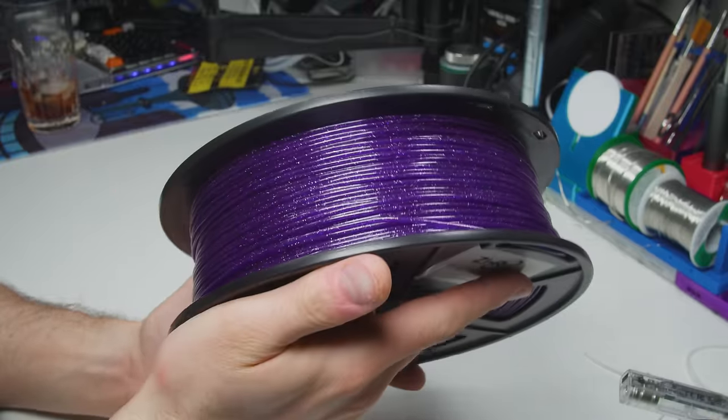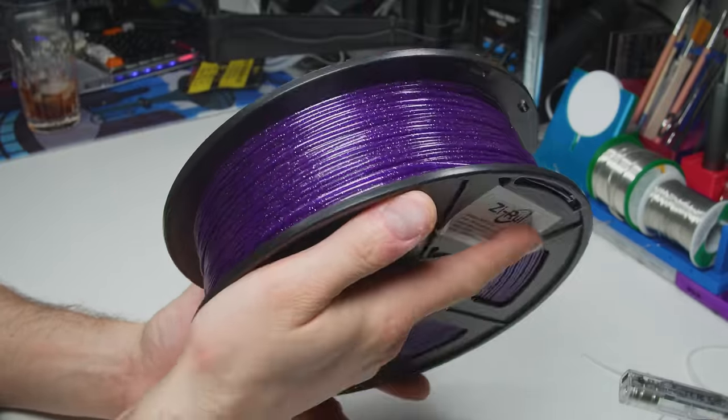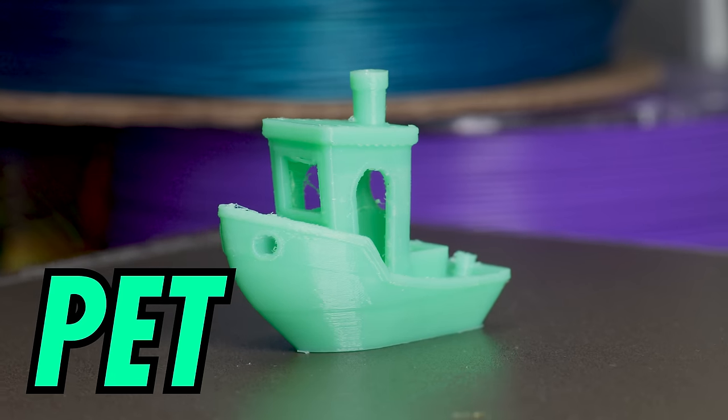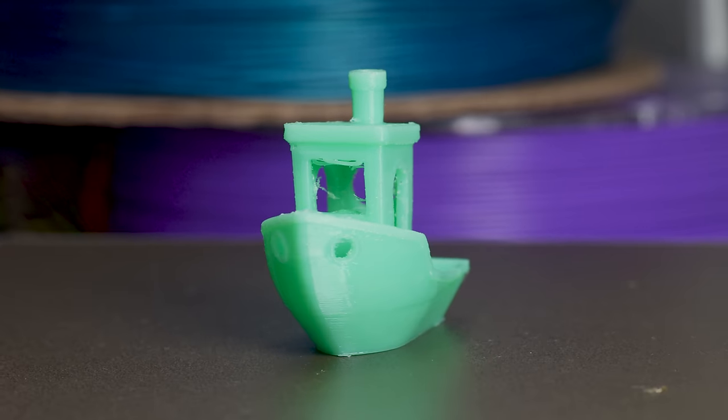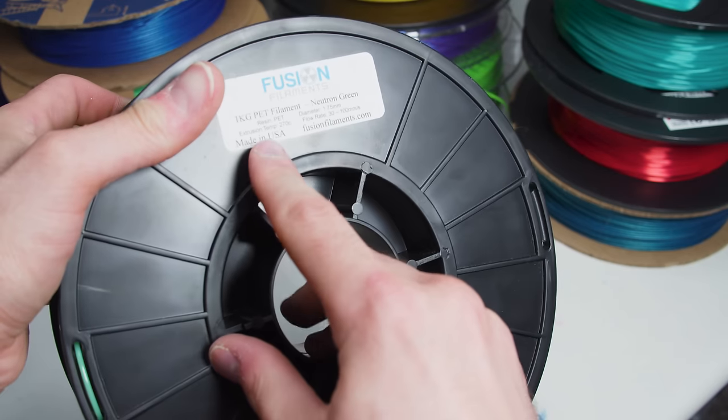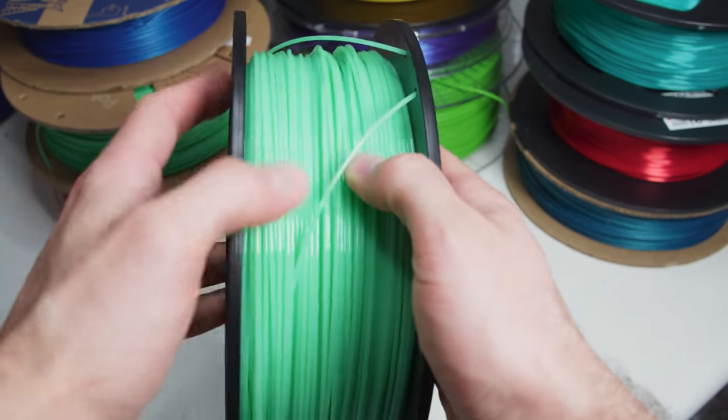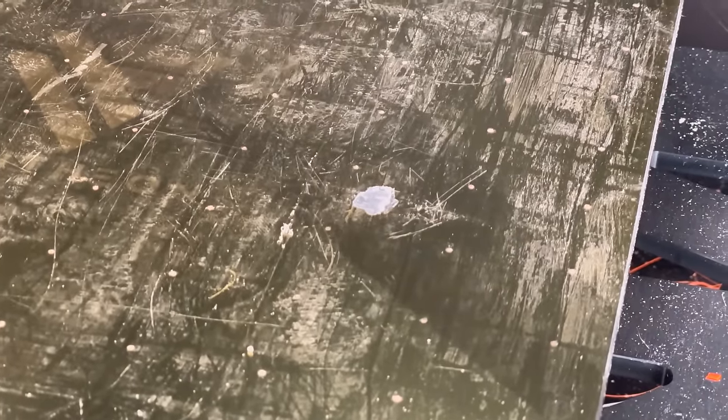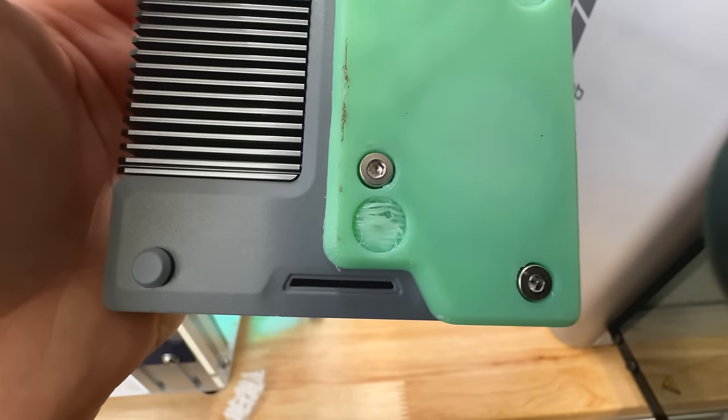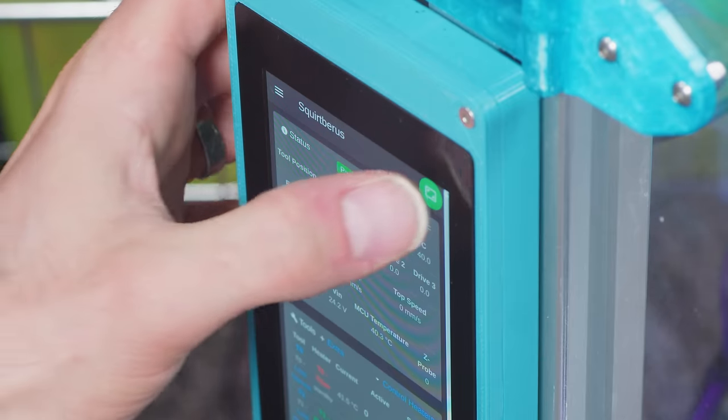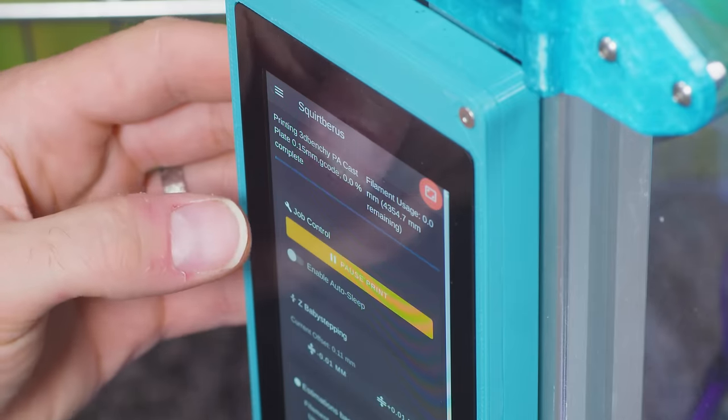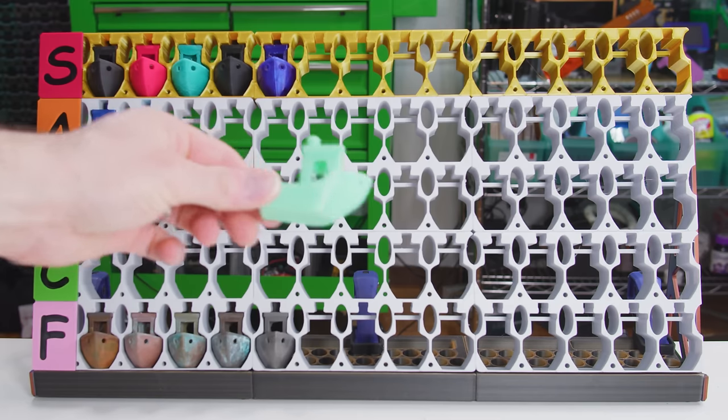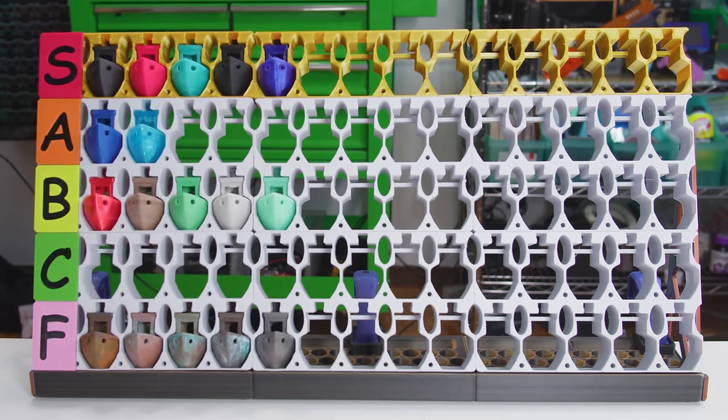That last letter, the glycol, makes the polymer more flexible and easy to print. But if you want to play in hard mode, hard as in challenging and as in stiff, you can leave the plasticizer out. The result is PET, also called BPET for bottle grade and HTPET for high temperature. This filament prints at 275 degrees minimum, ideally over 300. Compared to PETG, PET is stiffer, tougher, shinier, and absolutely devastating to bare glass and PEI. And of course, crazy resistant to high temperatures. It's basically super PETG. It shares PETG's problems with overhangs, warping, and humidity, except they're even worse. That said, it's easier and cheaper to print PET than other high-powered engineering filaments like nylon and polycarbonate. So I'm going to put PET in high B tier. It's got power, but you will suffer for it.